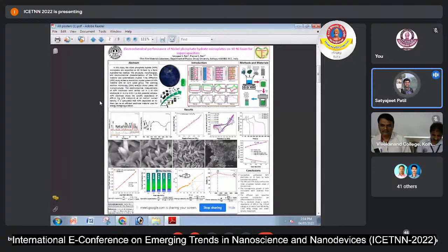The electrode's cyclic stability was studied up to 5,000 cycles. It shows 79.24% stability at the 100 millivolts per second scan rate. In summary, the electrode shows a specific capacitance of 855.12 farad per gram at 10 milliamp per centimeter square current density, with 66 watt hour per kg energy density and 1250 watt per kg power density. This comprehensive study suggests that nickel phosphate hydrate microplates are advantageous for improving energy storage.